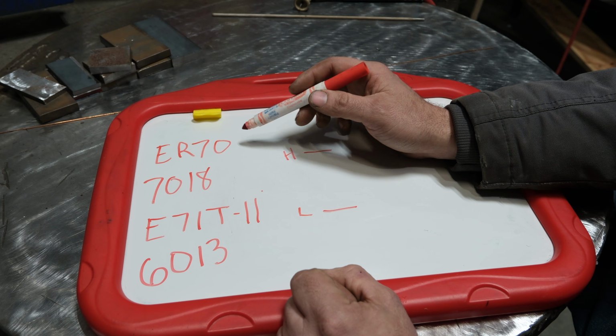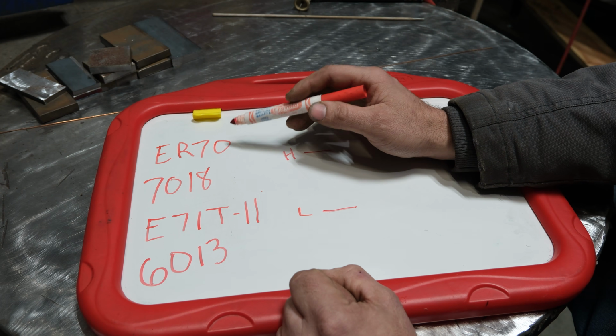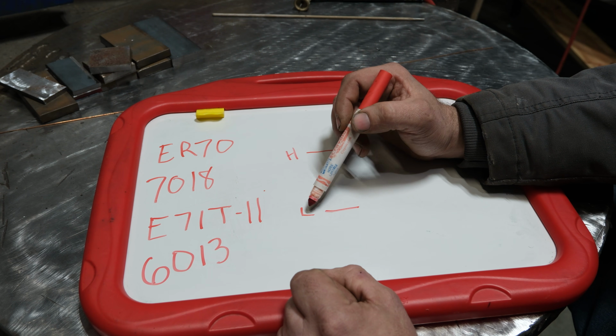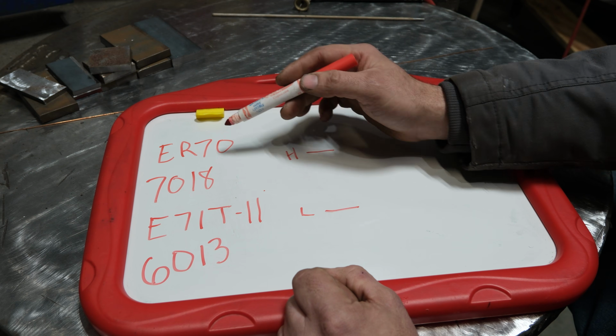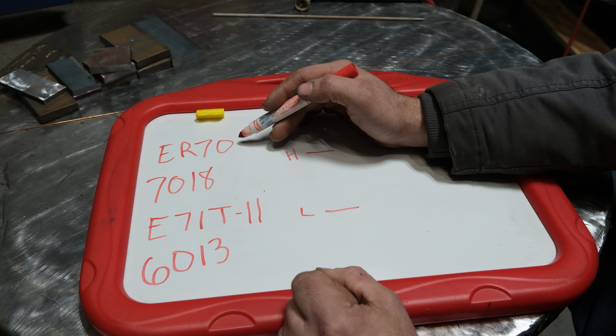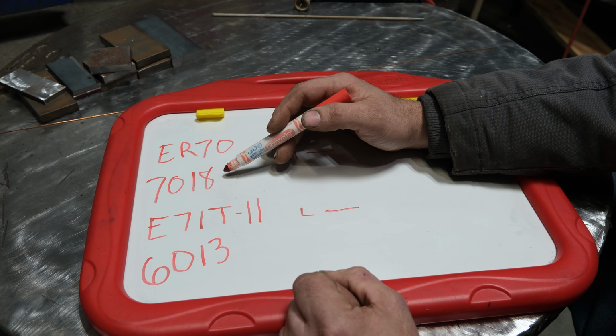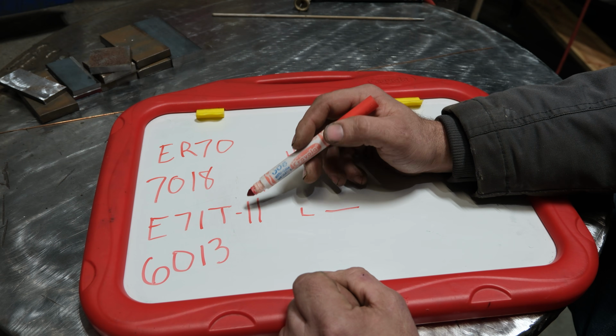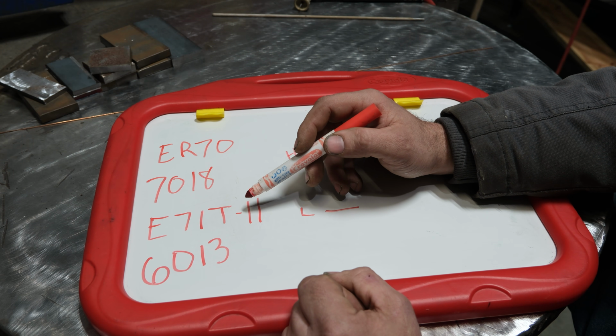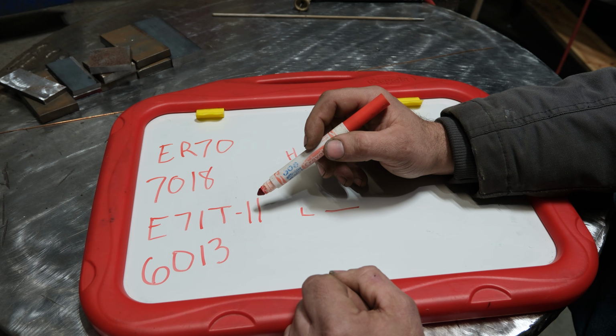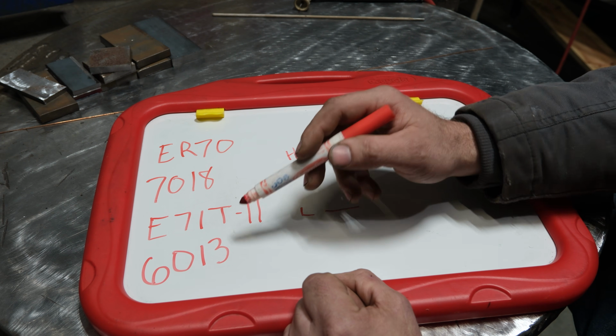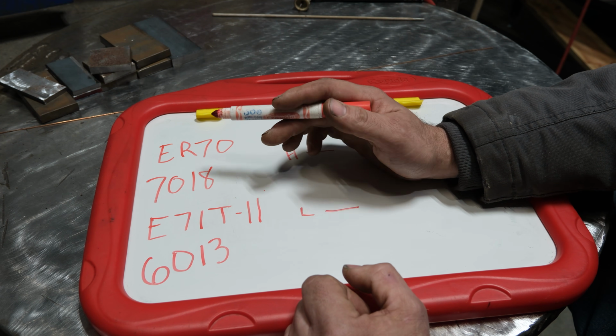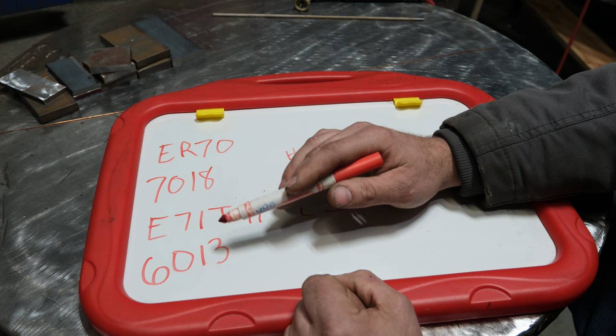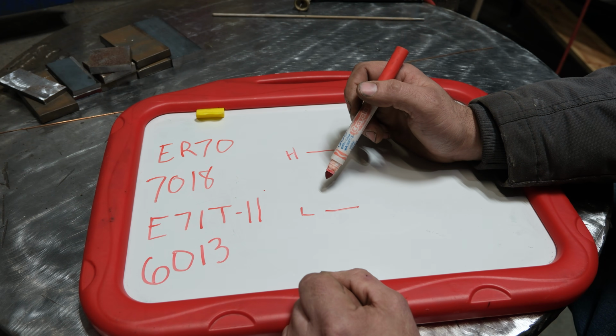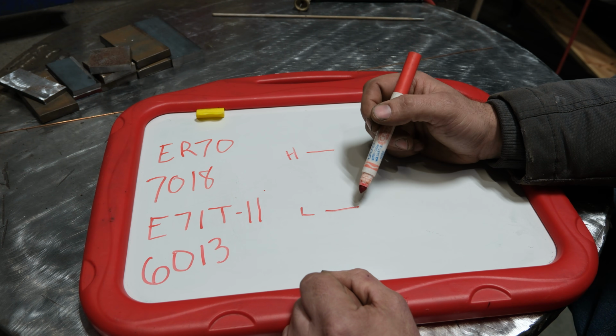All of these, and I'll put links in the description to some of the actual test results of these products, are all going to be significantly higher than the minimum in actual testing. So ER70 typically is 77,000 or more in actual testing. 7018 is between 78,000 and 81,000 from what I've seen on spec sheets. E71T generally is somewhere in the high 70s as well, sometimes as high as the low 80s. 6013, believe it or not, is typically in testing about 70,000. So it's actually higher than what its numbers would suggest. So again, all of these are the minimum.